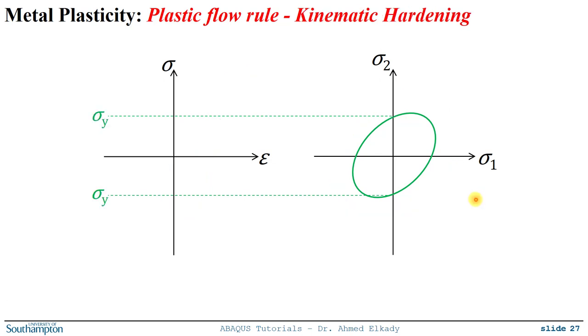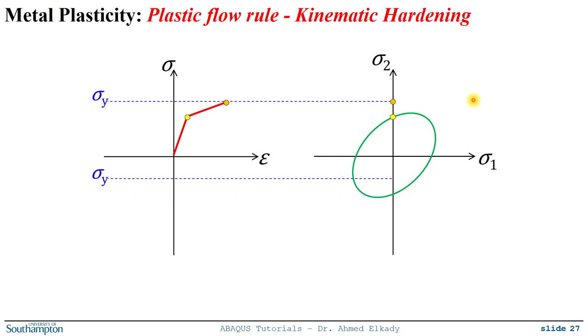So now let's see how the kinematic hardening works. So the same thing, if you start with loading, the first thing you reach is the first yield point of the first surface, and then if you push it further with some hardening into the plastic branch, and if you stop over here, what will happen is that your new yield surface will shift, and actually the size of this yield surface remains the same, but the center is shifted upward, as you see over here.